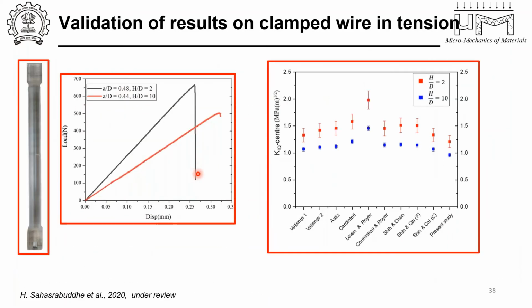So again, we did validation of clamped wire in tension, but this is not a wire. This is a rod specimen, again with PMMA, because that's the cheapest material that we could lay our hands on. And we measured the fracture toughness for two different H/Ds of 2 and 10. The value that we get, which is close to 1 MPa root-meter for the notch toughness, is closest to what is reported in the literature, whereas some of the solutions provided by other authors in fact overestimate the fracture toughness by a lot.